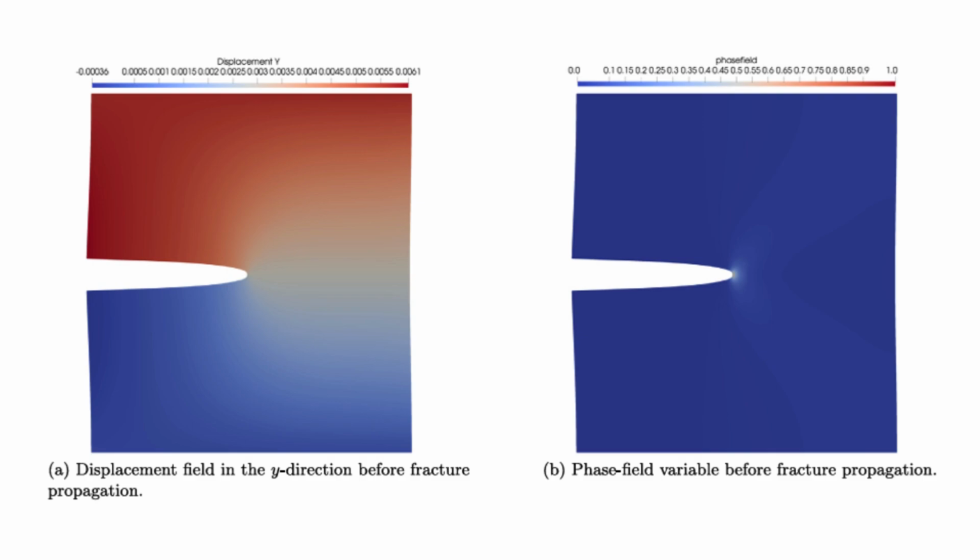They made a key choice. They prioritized robustness, maybe over raw speed. They used something called the alternate minimization algorithm, or AM algorithm. Alternate minimization. Okay, sounds logical. How does it work? Is it like solving one part then the other? That's exactly it. It's often kind of a staggered approach. You break the problem down. First, you pretend that the damage field is fixed, frozen in place, and you solve for the displacements, the elastic deformation.